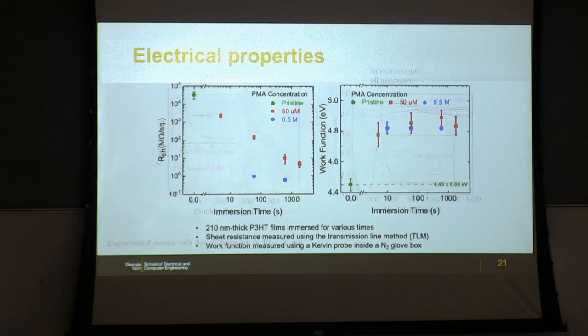And so here you see the changes in electrical properties. On the left, you see the sheet resistance of some P3HT films. In green here, upper left, you see the sheet resistance of a pristine P3HT film. And then you see here, depending on the concentration of the dopant, but in a high concentration, and after only about 100 seconds, you can see that you can modify the resistivity or the conductivity here by nearly five orders of magnitude.